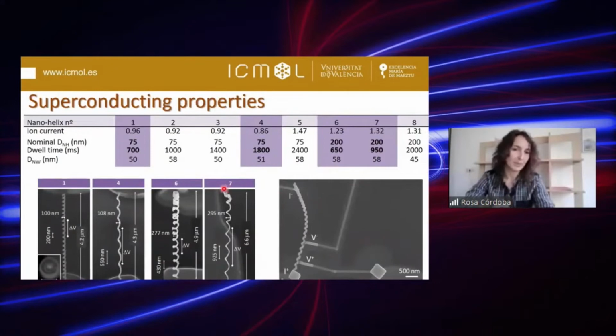Regarding the superconducting properties of these nanohelices, I studied a few of them for comparison. These two, type 1 and type 4, have almost the same diameter, around 100 nanometers, and the difference was the length of the tail, from 200 to 550. And type 6 and type 7, to observe that the properties were similar for nanohelices with 300 nanometers in diameter and modifying the tail length from 430 nanometers to 900 nanometers.